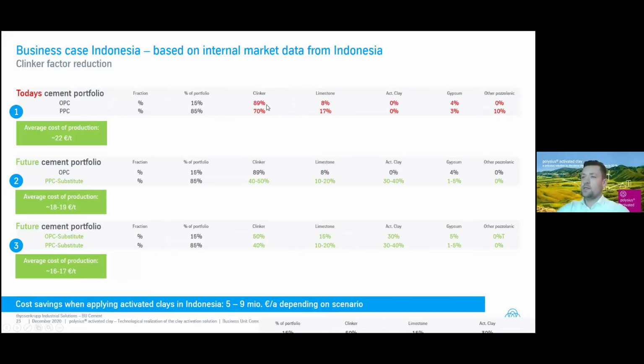So the OPC is containing around 90% clinker, 8% limestone, 4% gypsum in this case. This can vary from case to case for sure, but this is the basis for this calculation. And then we have the PPC, which is containing 70% clinker, 17% limestone, and 3% gypsum, as well as 10% other pozzolanic material. So this is our base case we just used for this evaluation here. We also received some costs for clinker, limestone, electricity, fuel costs, etc. And we did the first business case evaluation on this.